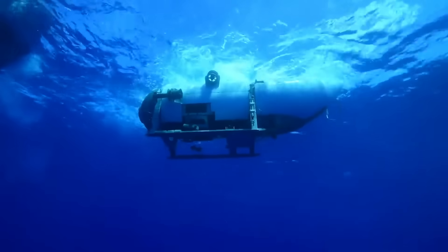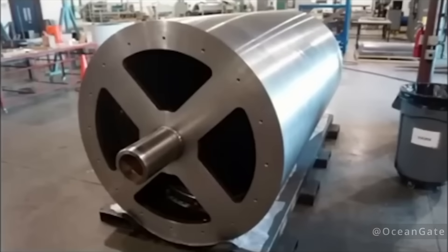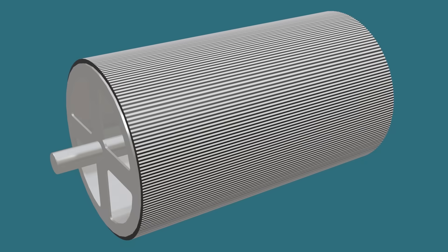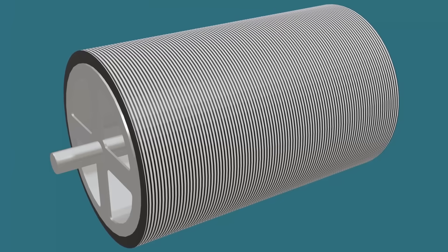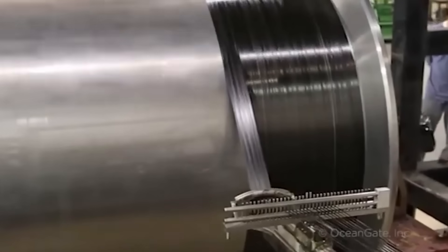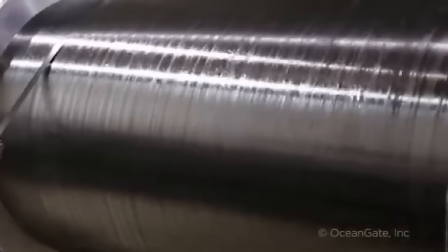Titan went through two versions of carbon composite mid-body tube. OceanGate CEO Stockton Rush describes the evolution: "The carbon fiber — this is the mandrel — this thing is an inch and a half thick. Filaments were laid down in alternating hoop and axial layers. We'd wind a layer and then do a longitudinal pre-pregged carbon fiber lay on top and built it up to five inches thick. I took it to 4,000 metres and it made a lot of noise, which is a very sphincter-tightening experience." Sub-owner Carl Stanley was on the second dive: "Every three to four minutes there was loud gunshot-like noises."